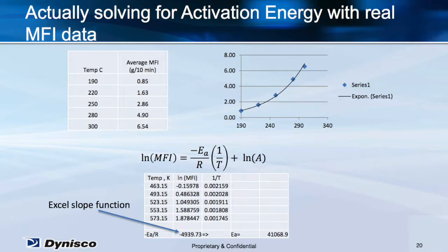In the bottom table, I converted the temperature to Kelvin as required by the Arrhenius equation and calculated the natural logarithm of MFI and 1 over T in columns 2 and 3. I then used the Excel slope function to calculate the slope of the line of columns 2 and 3. After that, I simply multiplied that slope times the value of the gas constant, R, times -1 to determine the activation energy.